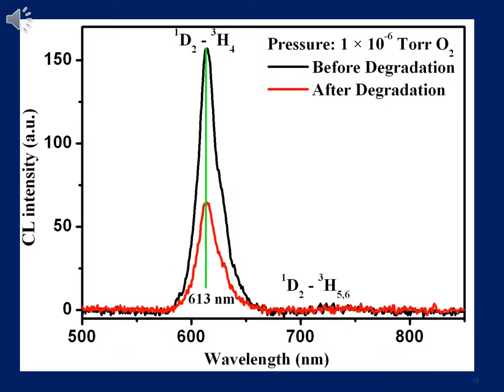Now, comparing the spectra before and after I exposed my material to a prolonged electron beam, I see that the CL intensity decreases from about 150 counts to about 50 counts. Now, this is clear evidence that the luminescence intensity has decreased, and we need to look into the species which are now forming, which are resulting in this quenching of the luminescence. And to do this, we have to do XPS measurements.